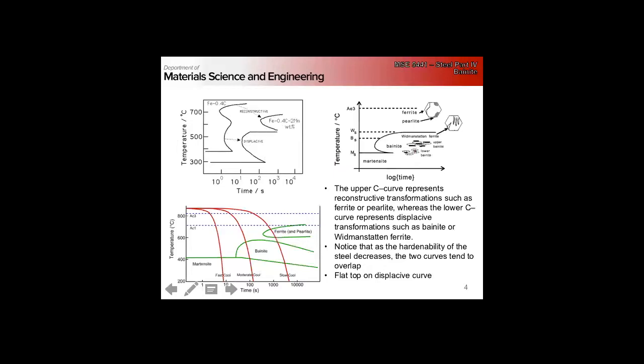This is pearlite and our idiomorphic and allotriomorphic ferrite up here. And down here is our sort of displacive mechanisms, Widmanstätten ferrite, Bainite. And you see this has got a really flat top, right? So that means there's just some temperature for a given steel that when we're above it, we're not going to be able to access any of the shear transformation mechanisms.